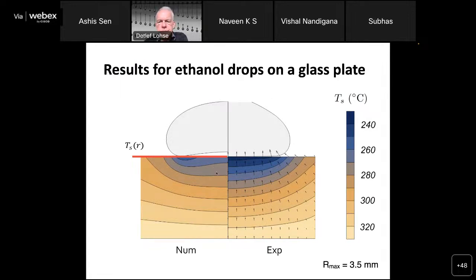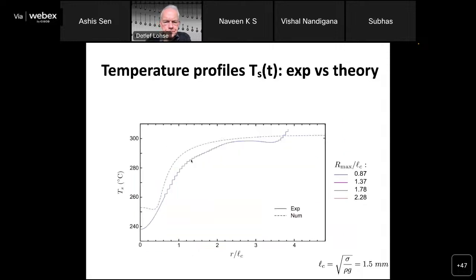So we assume axial symmetry, which is justified. And on the left, we show the numerical results, and on the right, the experimental results. And again, there's no parameter in here. And the temperature scale is given here. And it's not bad. I mean, it's not perfect, but it's really not bad at all to see this behavior here and the cooling down. The cooling down is considerable. You see here, we cool down to 240. Down here, it's 320. This is to what we set the substrate, but here it's cooled down to 240.